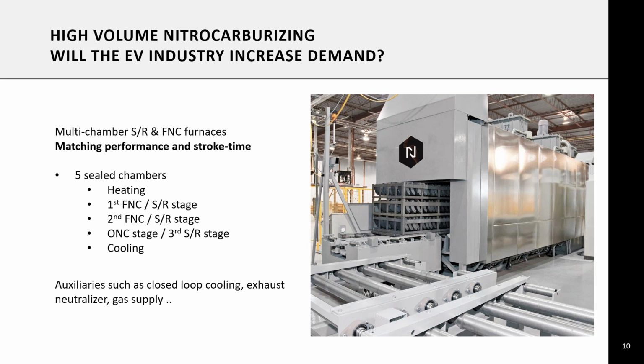Nitrocarburizing is used a lot for components such as brake components and chassis components, because it's a process specialized in sliding wear and anti-corrosion, among others. So the volumes have been increasing, which calls for completely different solutions. Most of the nitrocarburizing processes are relatively short, meaning that they last between less than 3 hours and perhaps over 6 hours. This means that big pit furnaces are not very practical because your heating time and cooling time requires a long time because of the volume and the weight, and the process itself is relatively short. Therefore, we are evolving towards equipment which is either continuous or semi-continuous to be able to provide solutions for this kind of demand.